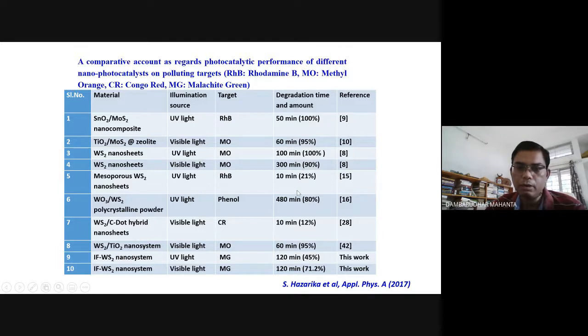So one can actually compare. So what I could see, the mesoporous WS2 nanosheets on rhodamine B up to 10 minutes, but again the performance is very low, which is about 21%. So keeping in mind all this literature survey, we found that this was rarely discussed in the literature, and we found that under visible light, this inorganic fullerene type nanocatalyst, if we have, we can degrade it quite efficiently.